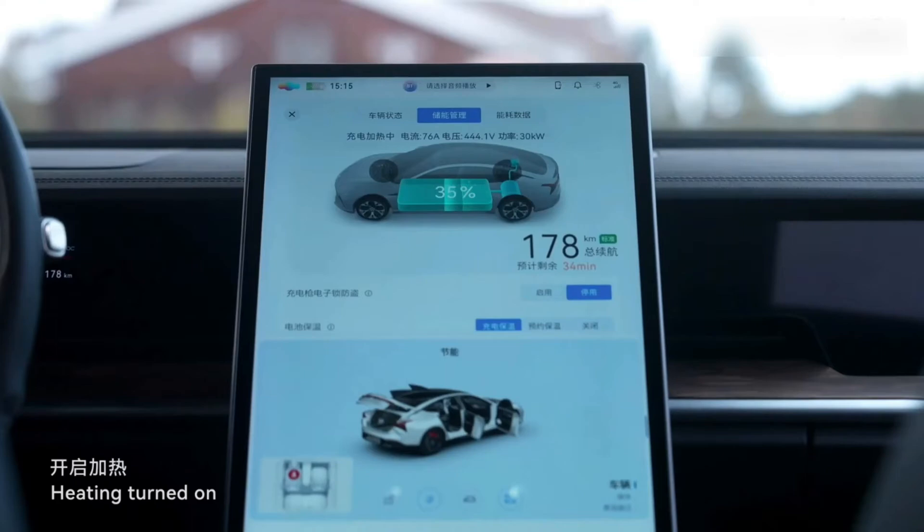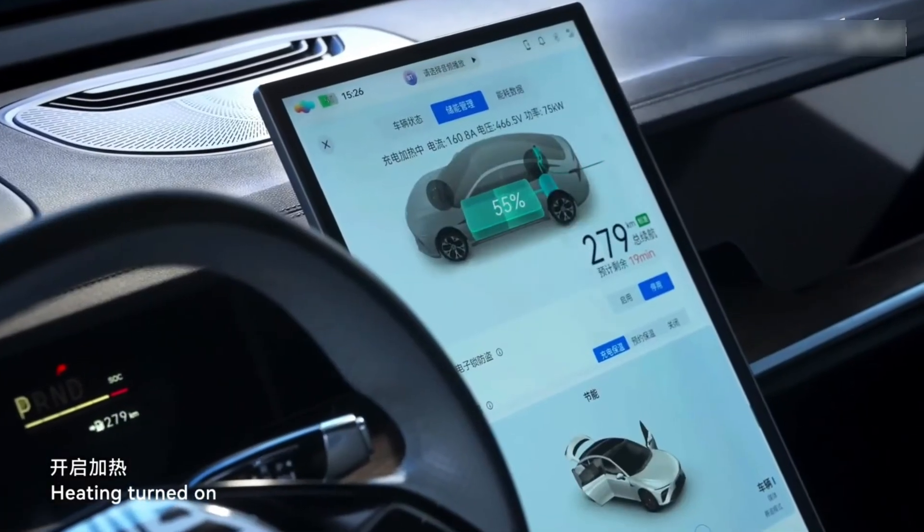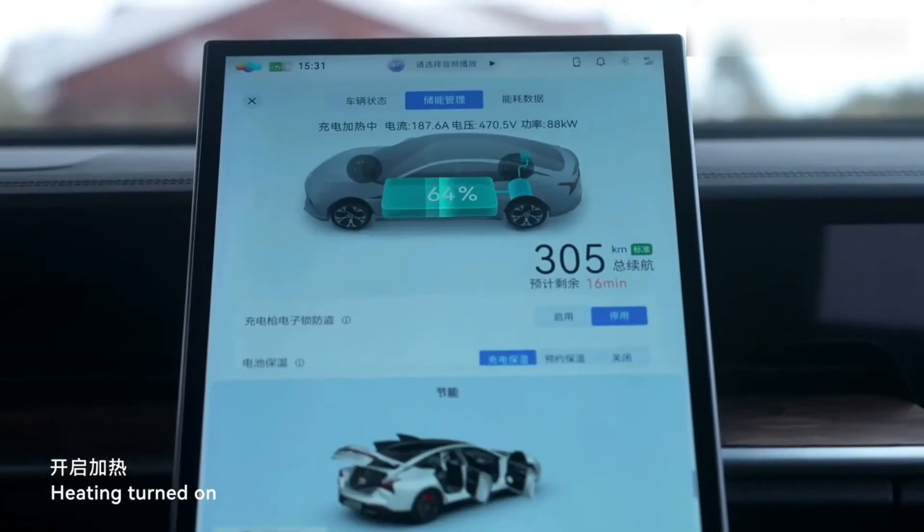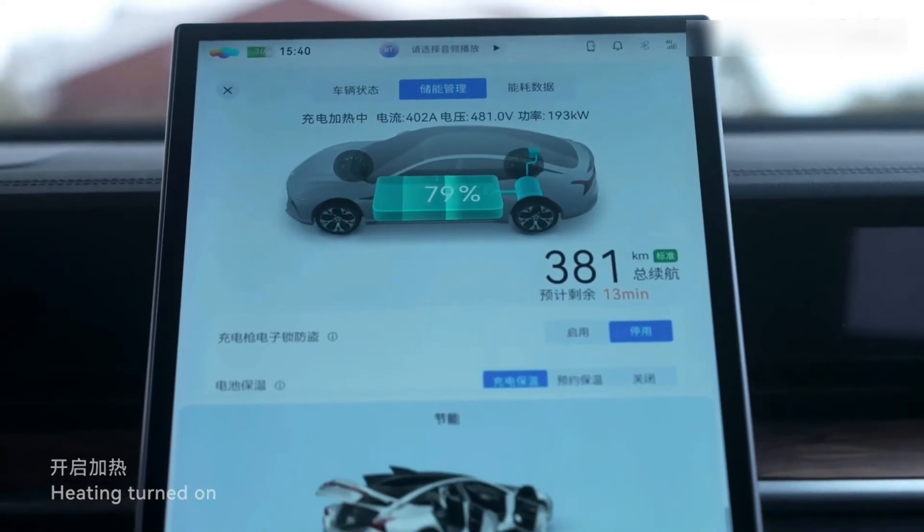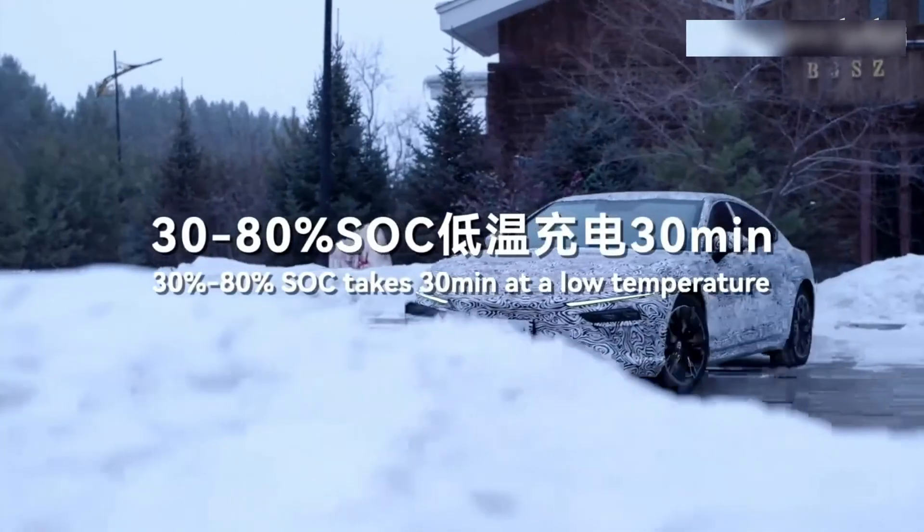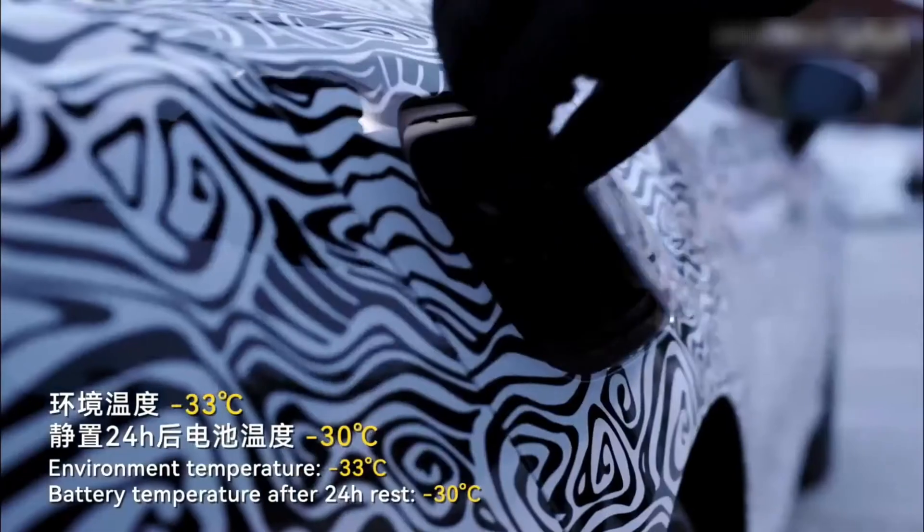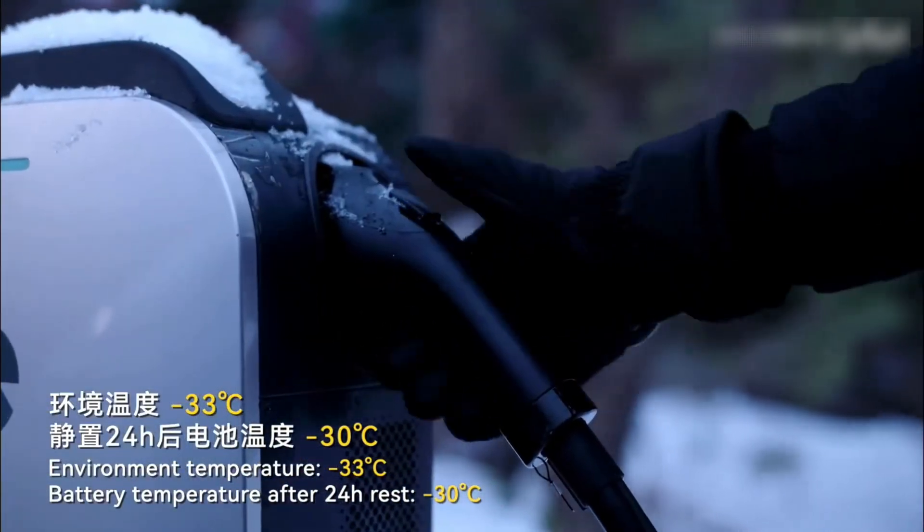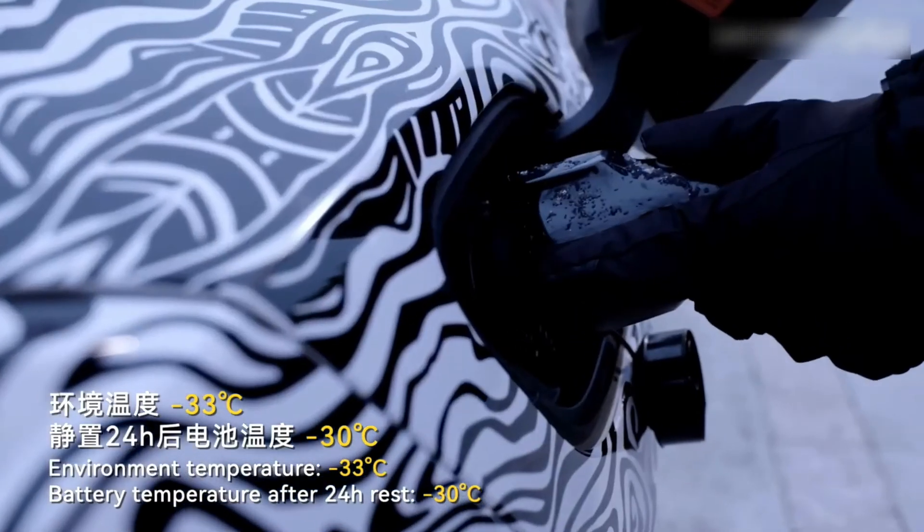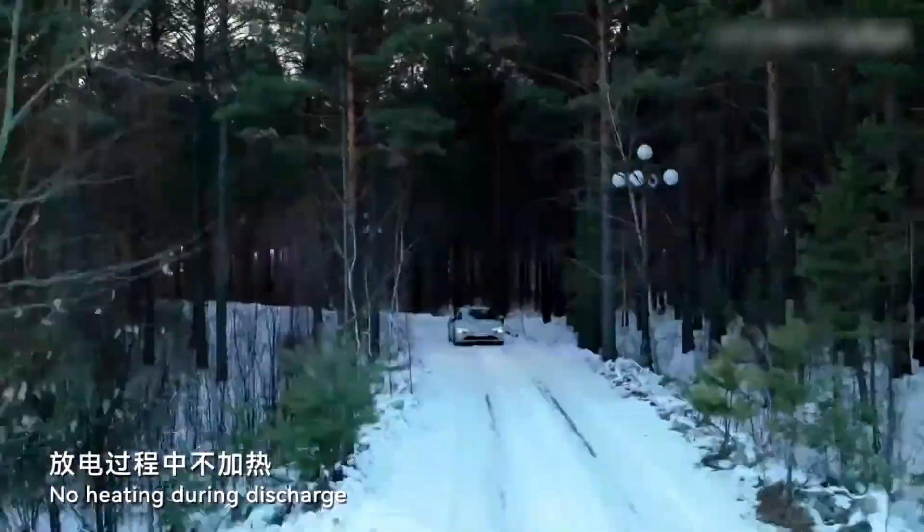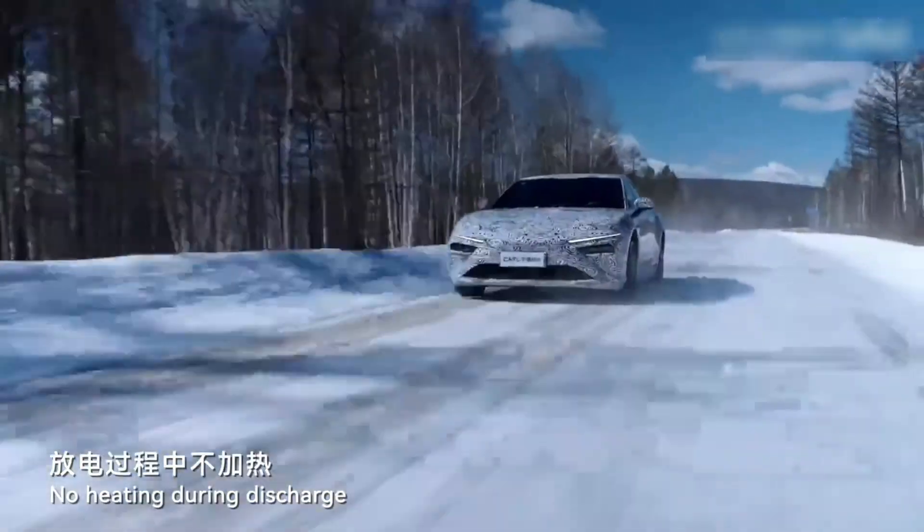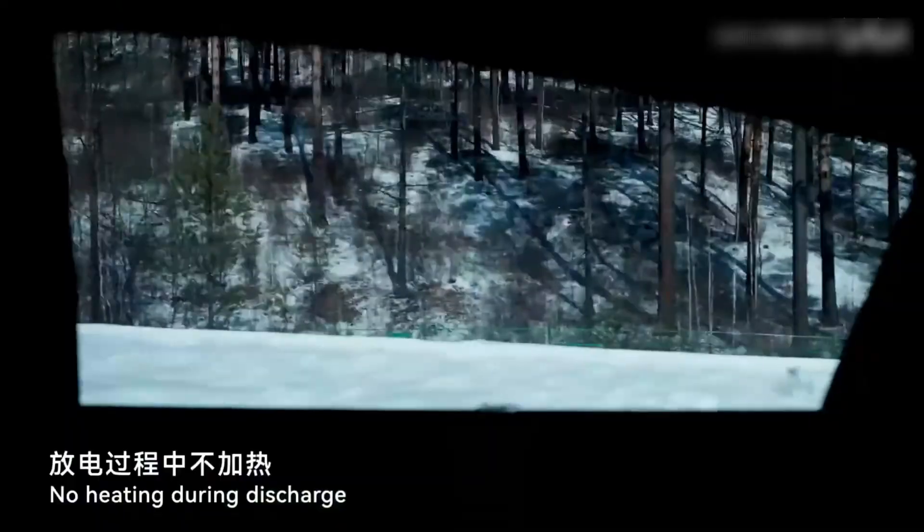While preheating is still required for charging in such extreme cold, the battery doesn't need to be warmed up as much as a typical lithium ion battery. And it charged from 30% to 80% in just 30 minutes, even when the outside temperature was minus 33 degrees Celsius. That's a dream come true for anyone living in cold climates. No more losing half your range in the winter.